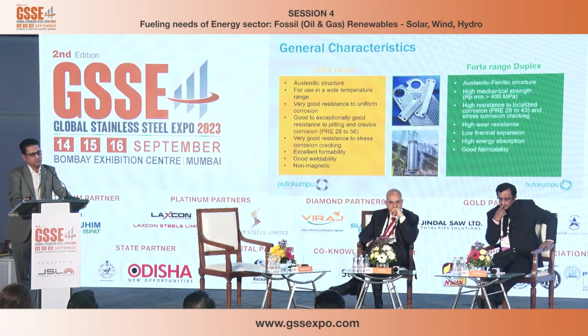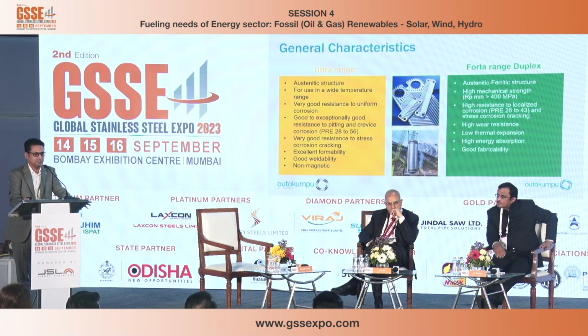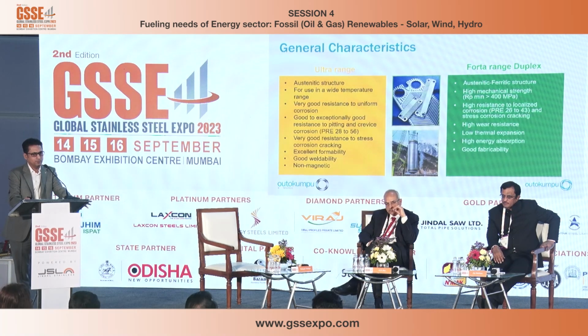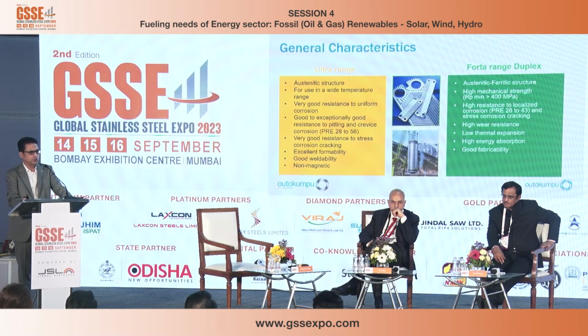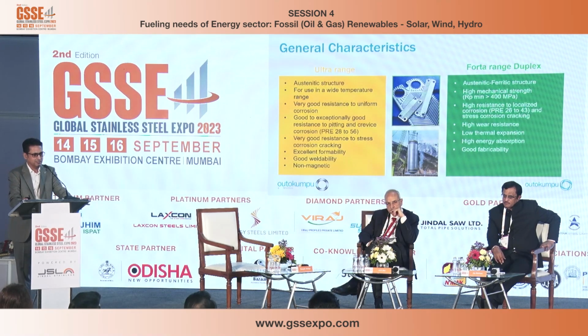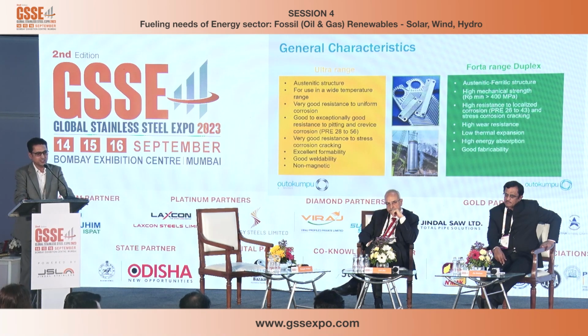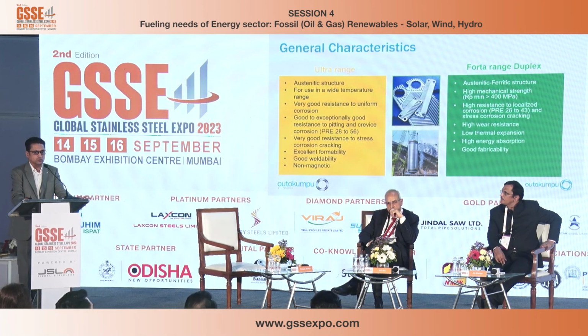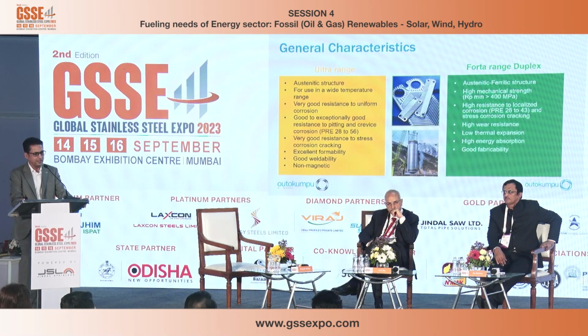But then there exists a solution with the Forta range, where it is an austenite plus ferrite structure in the same material. It can be used in a limited temperature range from -50 to 250 plus degrees centigrade. The PREN is from 26 to 43. Yield strength values are normally more than 400 megapascal. So you can use the strength of this material in comparison to the austenite to design your product. It has low thermal expansion, very high absorption and good fabricability.